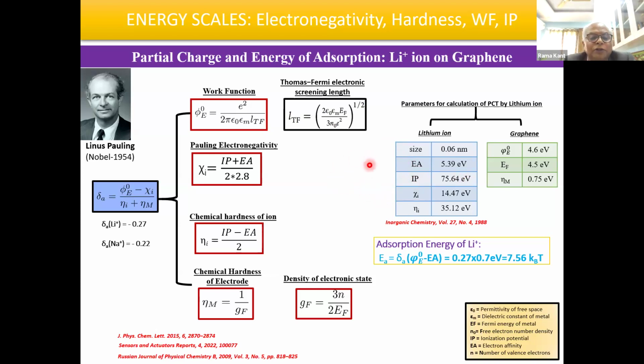So if you put all these things in, find this fractional charge, and how much energy of adsorption there will be, you take the fractional charge which we obtained from here, which turns out to be for lithium about 0.27 of an electronic charge, a fraction of that. And for sodium, it will be 0.22. And sodium is also large, so there will be a barrier. If I estimate this energy barrier, it is about 7.56 in units of mean thermal energy at room temperature.